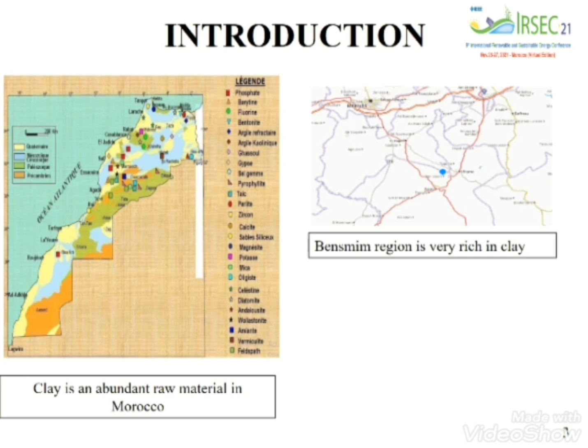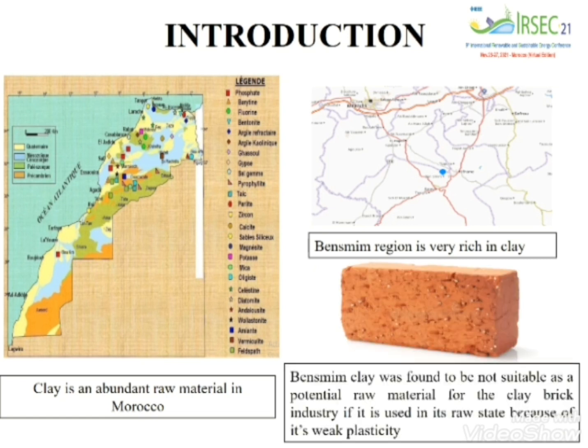For example, Bensmim is a mountainous region in the Middle Atlas situated near Ifrane city. This isolated poor village is desperate for affordable housing with decent thermal properties. The cheap, the natural, and the affordable raw material in this region is clay. Unfortunately, this clay was found to be not suitable as a raw material for the clay brick industry if it's used in its raw state because of its weak plasticity.